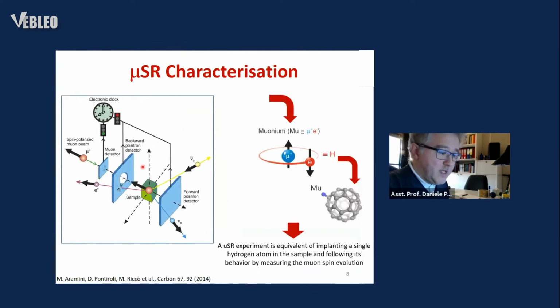In order to gain further information, such materials have been investigated with muon spin resonance, a peculiar and exotic technique consisting in the implantation of polarized positive muons in the sample and in the study of the precession of the muon spin as a function of time. This can be done since muons decay with a half-time of a few microseconds, emitting a positron in the direction of the spin. Positive muons chemically interact with the electrons of the carbon backbone and form muonium, which is a light isotope of hydrogen. Hence, a mu-SR experiment is equivalent to implanting a single hydrogen atom in the sample and following its behavior by measuring the muon spin evolution.